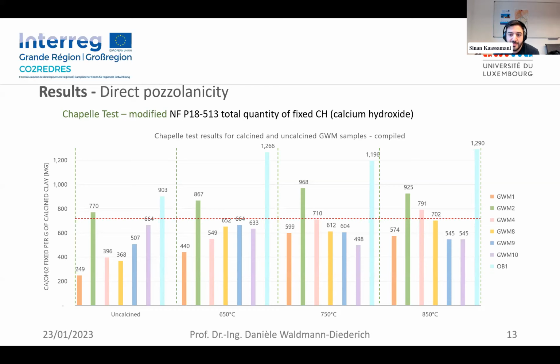But it's interesting to actually see that many of our materials, we didn't pick and choose, right? These are the materials that we had from our partners. So no extra sieving to take out the quartz was done. So it's basically trying to actually see the full potential of these materials as they are. So we can compare here the reactivity of uncalcined clays to the calcined ones at the 3 different temperatures, right? And it's an important result because it shows us that the materials are in fact improving their pozzolanicity after calcination at temperatures that are relatively low if we compare them to the temperature of the kilns, right? And this is expected to give us reactivity, right?